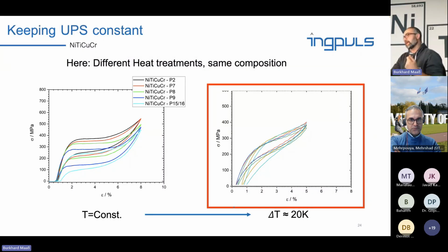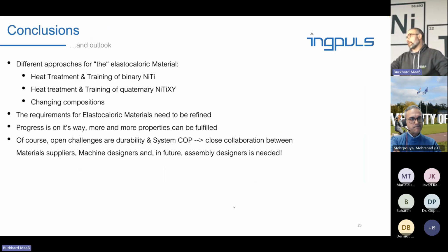And here was just one composition, and we can now have different heat treatment parameters. We can change the composition, and with this method, we can create material systems, material cascades for a very large temperature span, and that allows our partners to build better elastocaloric regenerators. That's for now for the conclusion.